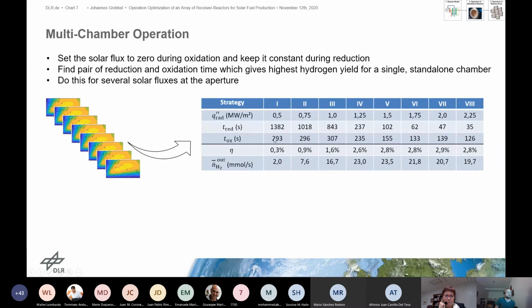And you can also see that, for lower fluxes, the oxidation time remains quite similar. And here at the higher fluxes, it also decreases. This is because here you don't want to spend too much time in the oxidation phase when you have such short reduction times. Interesting to see is also that the efficiency peaks at a different point than the hydrogen yield. And this is due to the different ratio of oxidation time and reduction time here.